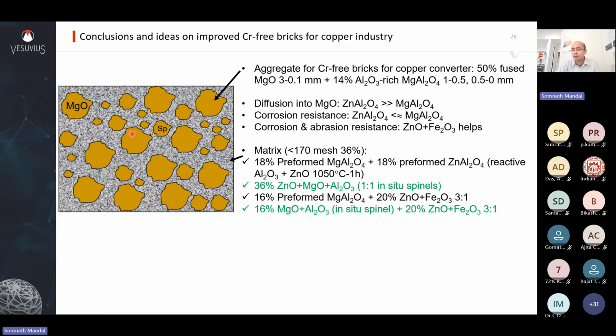You don't want iron doping in for steel making applications. This is specifically for copper application. The slag resistance will be good at those high temperatures. I have seen papers from Brazil who have tested refractories based on zinc aluminate, and they have found better corrosion resistance versus just magnesia spinel or alumina spinel. Generally with zinc aluminate, you only want partial substitution. It works the best, and that gives better corrosion resistance.